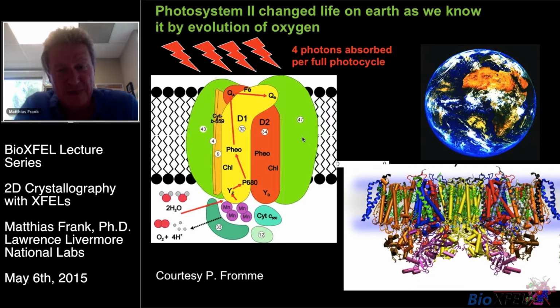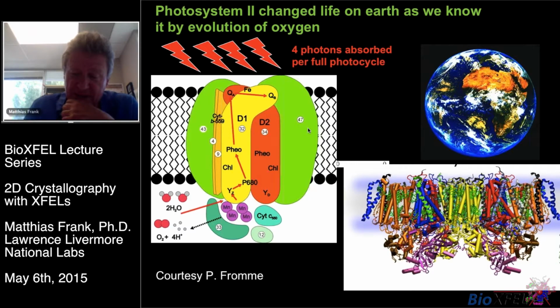What I mean with this is the reconstruction of the diffraction data does not require any prior knowledge about the protein structure itself. And the way they did that is they labeled the protein, and I believe it was lysozyme. They labeled it with gadolinium, which is a heavy metal atom, and that leads to some anomalous effects in diffraction that can be used for phasing. So anomalous diffraction was one of the methods that can be used to overcome the phase problem, and so this was demonstrated, and pretty much checked off that de novo phasing can be done at FELs.